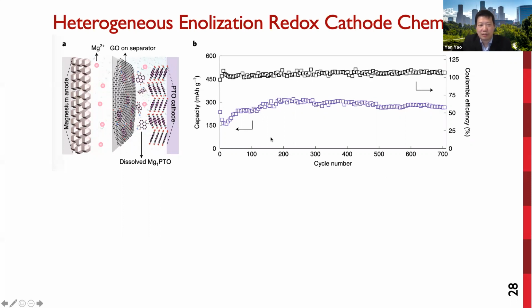The battery has an initial activation step due to the high viscosity of G4 electrolyte. Then it becomes stable for 500 cycles with a capacity retention over 84%.